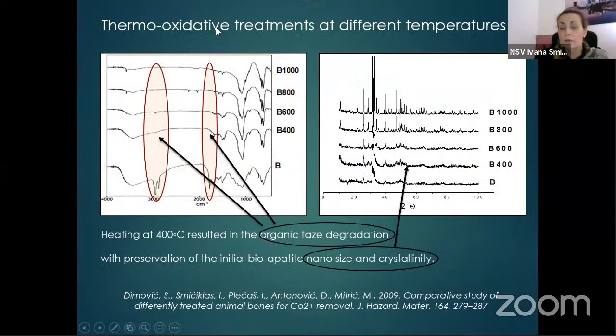Our group has performed experiments regarding the temperature during the thermo-oxidative treatments of the cow bones. We have applied various temperatures. We have obtained products with very different characteristics. These products were analyzed by chemical and instrumental analysis, and what we could conclude is that the organic phase of the bone is destroyed at 400 degrees Celsius and at higher temperatures.